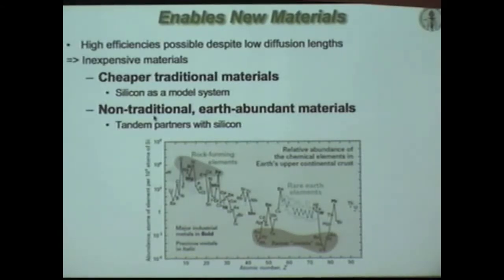It's heretical for an inorganic chemist, but the important point is that there are materials like zinc phosphide, like iron sulfide, like iron oxide, that are above this line, that are earth abundant, that you would never make planar solar cells out of because they can never be made pure enough, cheaply enough, to satisfy that planar ground rule constraint. We can just change the aspect ratio of these structures and we think open them all up to work.